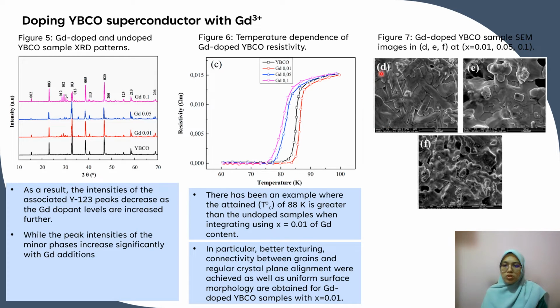Figure 7 shows the Gd doped YBCO sample SEM image in D, E, F at x equal to 0.01, 0.05 and 0.1. In particular, better texturing, connectivity between grains, and regular crystal plane alignment were achieved, as well as uniform surface morphology, for the Gd doped YBCO sample with x equal to 0.01.